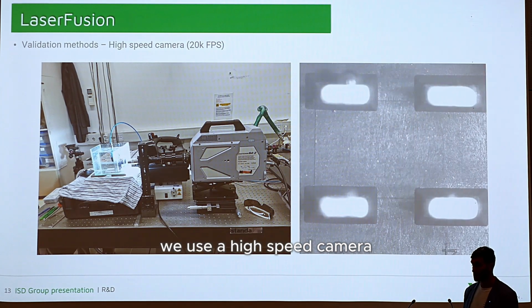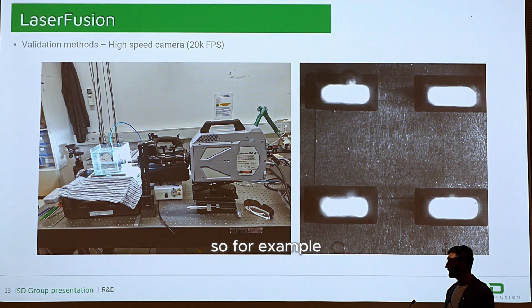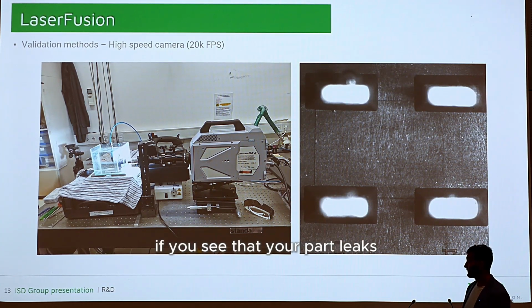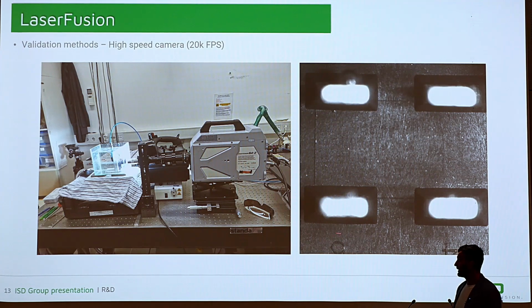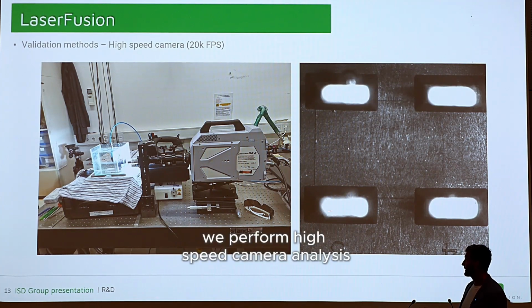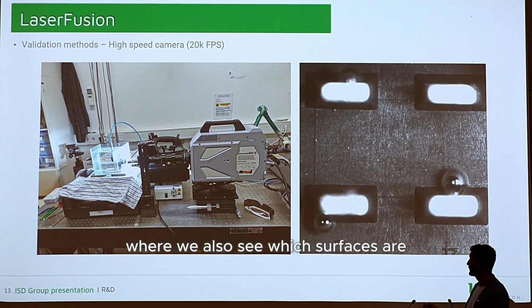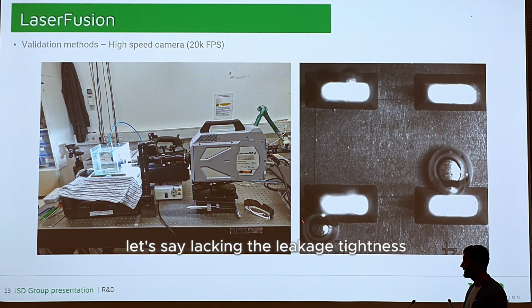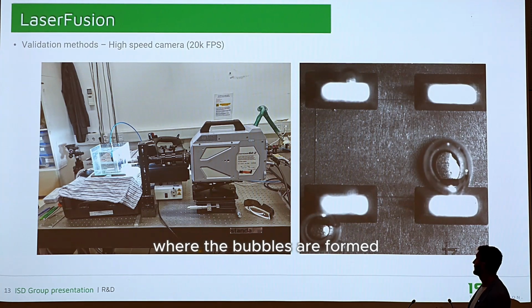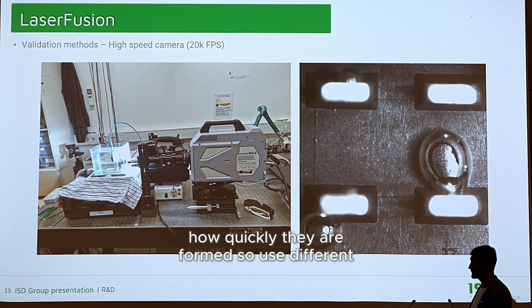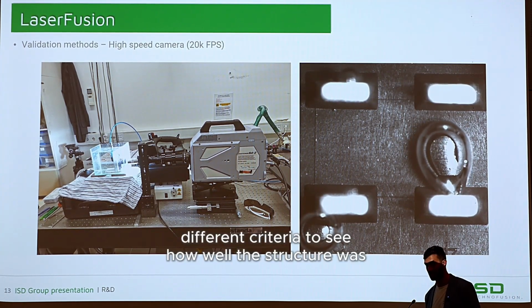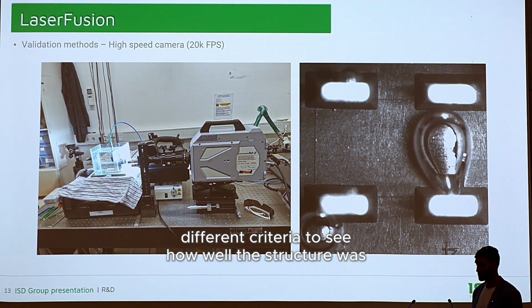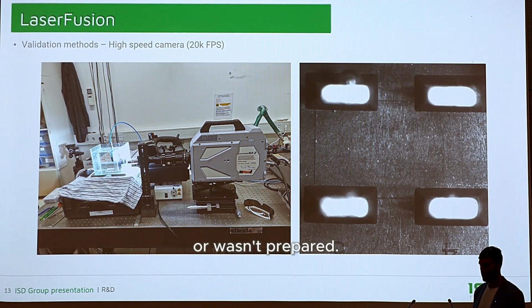The first one, especially for leakage tightness, is we use a high-speed camera. So, for example, if you see that your part leaks, we perform a high-speed camera analysis where we also see which surfaces are, let's say, lacking the leakage tightness, where the bubbles are formed, how quickly they are formed. So we use different criteria to see how well the structure was or wasn't prepared.